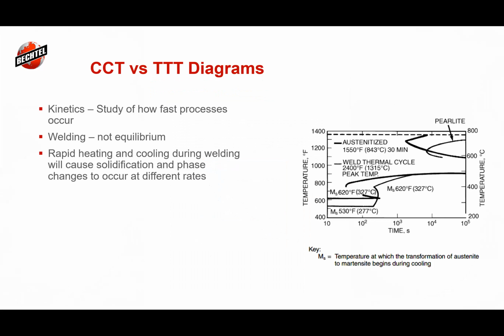I want to talk real fast about continuous cooling diagrams, and this can get more into welding. If you really are dealing with a new alloy, it can show how the cooling cycle, not only the rate of cooling, shifts some of these time temperature diagrams. So a fast weld cycle versus a slower weld cycle. I think there are a lot more of these in the welding handbook, I believe volume 1. It's again the phase diagram, and where these come into value is if you have a lot of experience with one of the T1 alloys and you're going to shift over to another high strength steel, you can compare your existing welding procedure to the new material that is similar but slightly different.